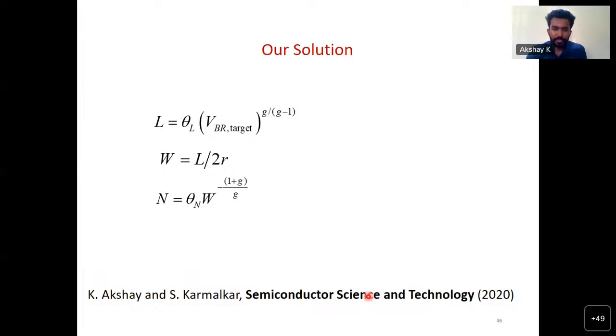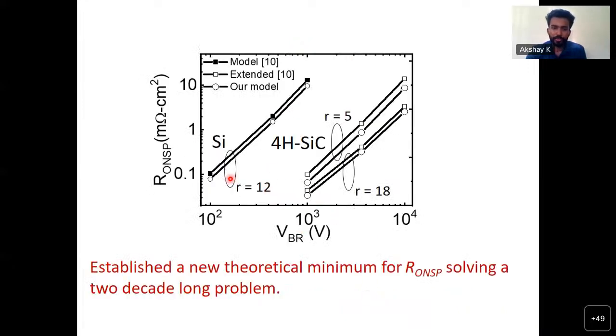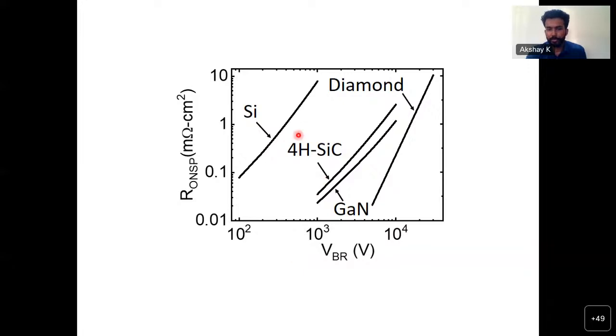So calculations using those models show that the specific on resistance for any given breakdown voltage, be it silicon or silicon carbide material, our model is predicting 30% lower specific on resistance as compared to the prior models. And thereby we could establish a new theoretical minimum of the specific on resistance, solving a 2-decade long problem. Why 2-decade long problem? The model previously published for solving this problem was 20 years back. And since then there was a research gap, and people have been using that same 20-year-old model, even recently. So by this model, we could establish new theoretical minima. That's with the ideal superjunction case. And we had also shown calculations for other materials as well, just theoretical predictions, diamond, gallium nitride, and so on.